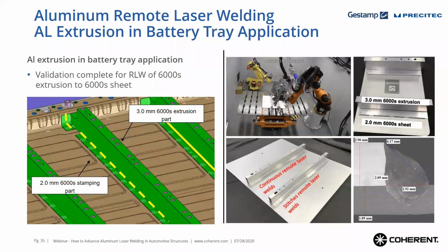Here's another one where they use an aluminum extrusion for a battery tray application. You have a 3 millimeter thick extrusion part, in green on the left side in the image there, welded to a 2 millimeter thick 6000 series stamping part. And you can see on the right side the results. They did both a continuous remote weld as well as a stitch weld on the bottom area there. And the bottom right image shows you the resulting fillet weld that they achieved, which was again very successful, done with the ARM fiber laser.